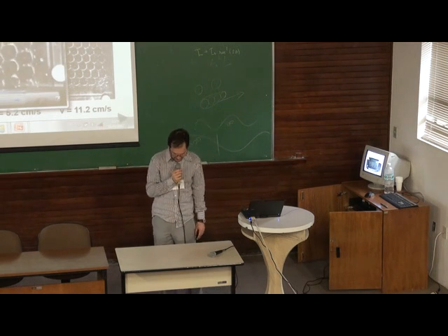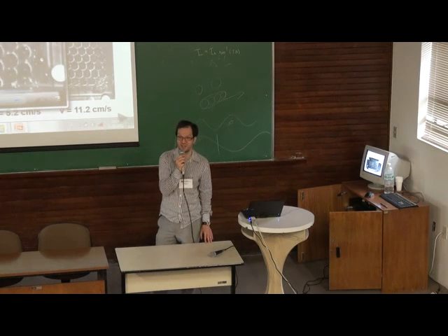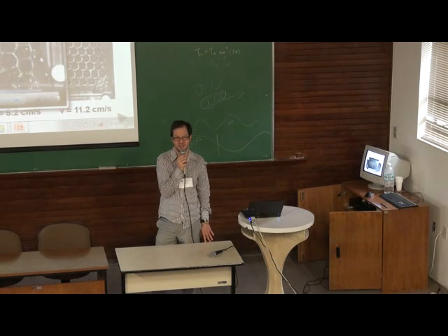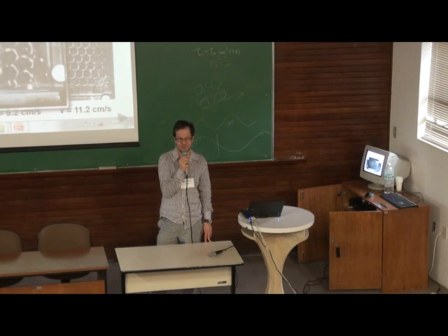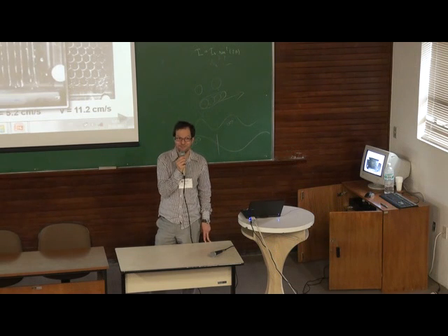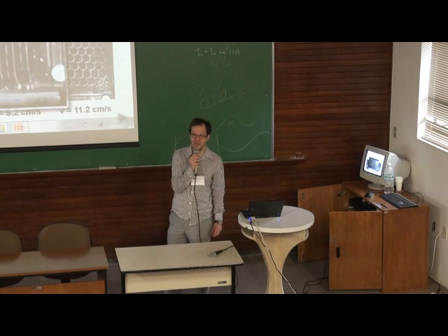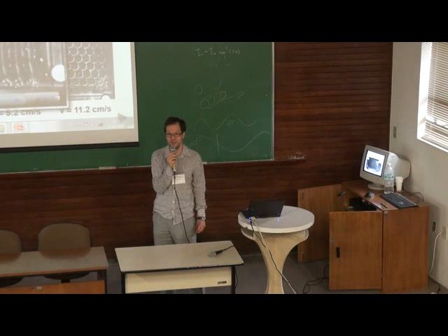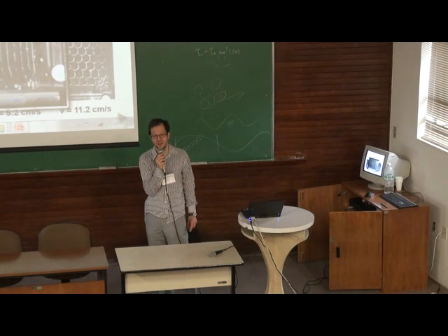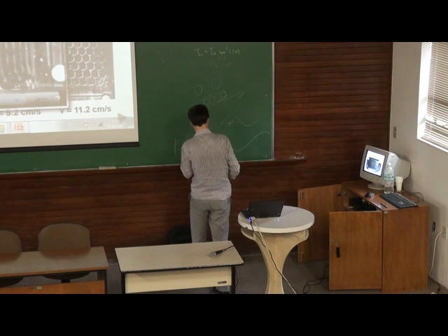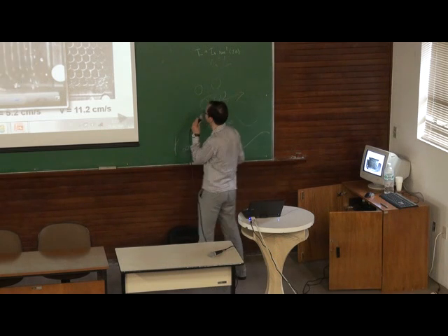In this kind of magnetite, the coupling parameter is rarely above 4 or something. Well, it's actually difficult, because one has to discriminate between the standard magnetic particle and something which is called primary agglomerates. These are some kind of artifacts during the production process.